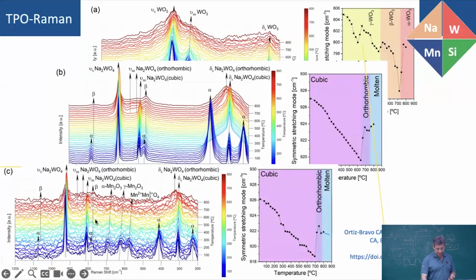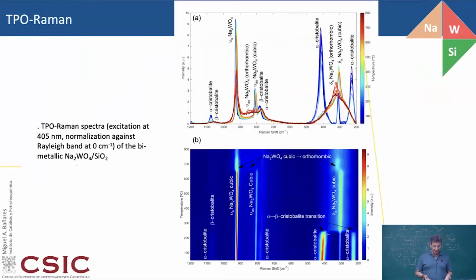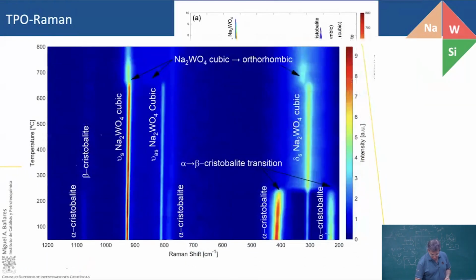And if you also have manganese in addition to that, the pattern is very similar. You go from cubic to orthorhombic and molten, but the temperature at which you go from the orthorhombic to molten changes when you add manganese to this sodium tungstate. If you look at the Raman spectra in detail, many things are happening there, and you can observe the evolution of the Raman bands.